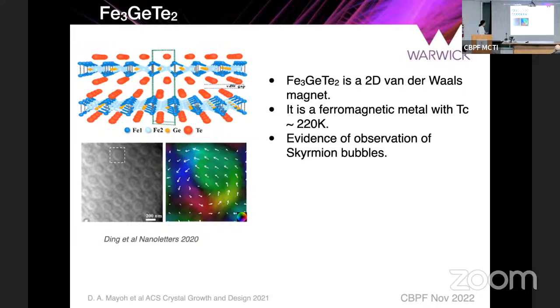The interesting thing about this structure is that it's a ferromagnetic metal, and the TC is around 220K. Now, I've been very modest in saying it's 220K, but you will see reports where they quote the TC as being much higher. Now, this is drastically high for a layered 2D material. I don't think there's any other material with such a high TC as a 2D van der Waals magnet.